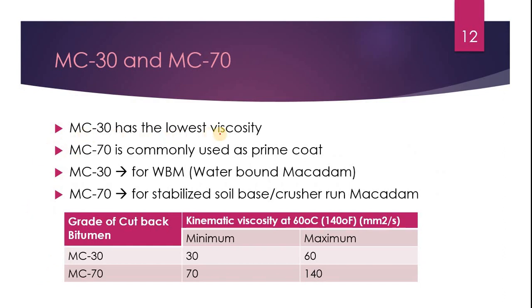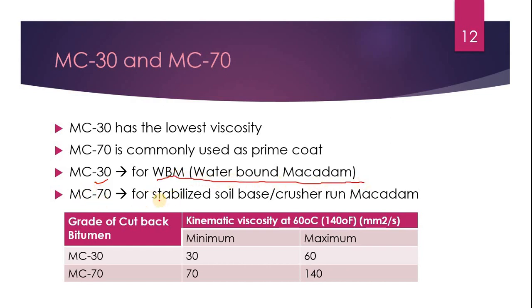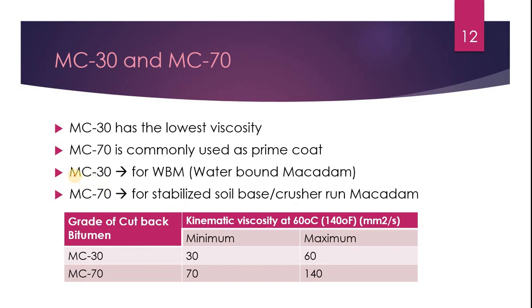MC30 has the lowest viscosity among MC grades. In the table: MC30 means minimum viscosity is 30 and maximum is 60; MC70 means minimum viscosity is 70 and maximum is 140. MC30 is used when the base is water-bound macadam, and MC70 is used when stabilized soil or crushed stone macadam is used as the base — both for prime coat or tack coat applications.